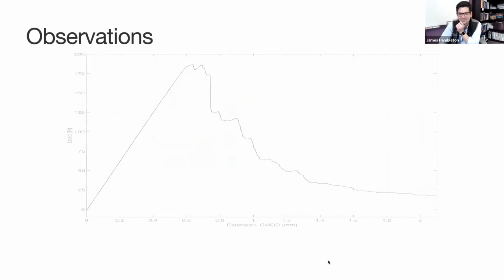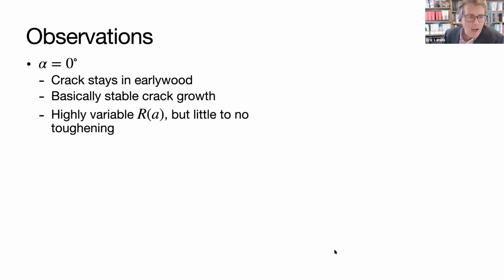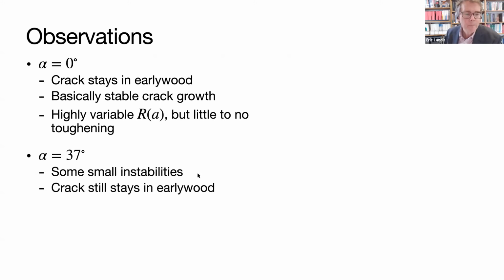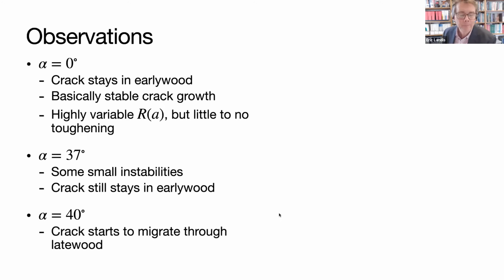All right, so some observations summing up what we've seen. So alpha equals 0. So now we're propagating a crack in the tangential direction. Basically, the crack stays in the early wood, and we have very stable crack growth. We have a high variability in crack resistance, but we don't really see any toughening. We increase that angle, and now we start to see some instabilities, but still the crack stays in that early wood, propagates along in that tangential plane. But at some point we see a transition where now the crack wants to maximize energy release rate, so it starts to migrate through the late wood.